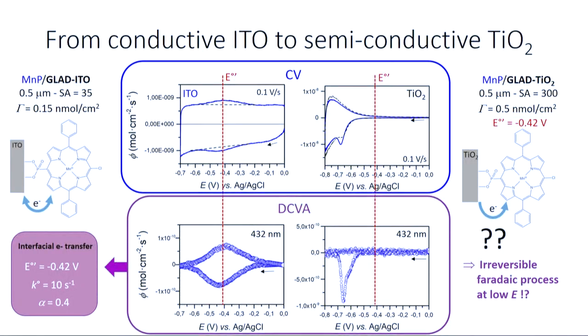And now I move to the second part of my presentation. I want to come back to this manganese porphyrin that I initially presented. What happens if, instead of immobilizing this porphyrin in a fully conductive glad indium tin oxide electrode, I now immobilize it in a semi-conductive glad titanium dioxide electrode? What we have shown previously, and this is what I already showed you, is that in indium tin oxide we have a reversible electron transfer at the interface. We have a huge capacitive current for the high surface area electrode, and we can get all the information about the reversible electron transfer, which is centered, obviously, at the formal potential for the manganese 3, manganese 2 redox transition.